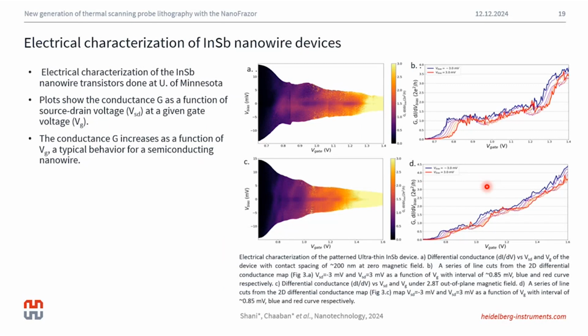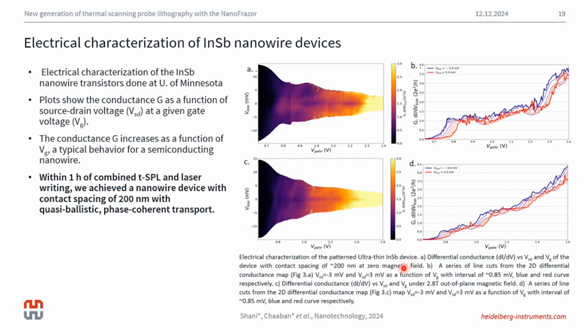Once we finalized the devices, we sent them back to the University of Minnesota, who was able to electrically characterize these devices. You could see the resulting graphs here. And what they found is that we could achieve quasi-ballistic phase-coherent transport across this 200 nanometer gap. For more details, I invite you to check out our paper, which was published just this year. What I'd like to also mention is that this large area device was written within 1 hour, both for the TSPL and the laser writer.